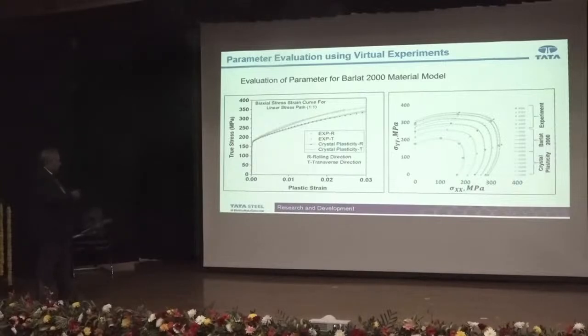Now this is the validation of such an approach with a biaxial experiment. So here we did an equibiaxial experiment also in this material because we have that facility. And we did this crystal plasticity based simulation, and then we checked whether it is working or not. Here you can see the match is very good, and this is the experimentally found yield surface and the validation of that with the different models also. So it was very well represented.